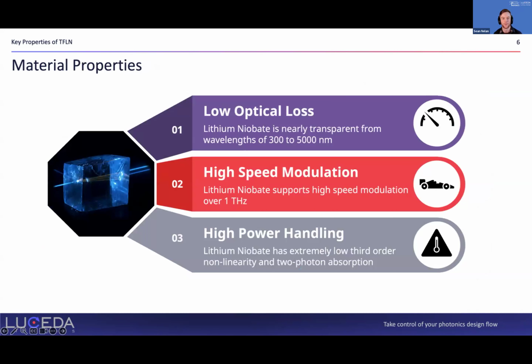So what are the material properties of lithium niobate that make it so interesting to us? First and foremost, low optical loss. None of us want our light to go away on our PIC. So lithium niobate is nearly transparent from wavelengths of 300 to 5,000 nanometers, or 0.3 microns to 5 microns. And that is a huge range when we think about photonic materials that generally only see a transparency window of maybe 500 to 1,000 nanometers. So this material can be used across a wide variety of applications.